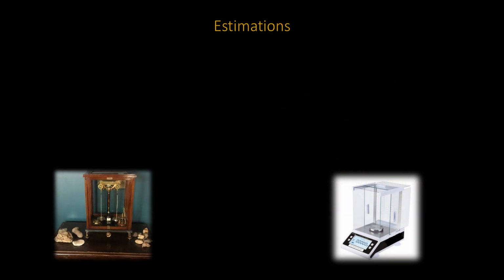It is important to estimate the amount of silver in the bead. This is usually done by conducting a preliminary parting without inquartation. This is done by weighing the doré bead prior to parting and then weighing after the parting. The weight in silver is estimated. It is the difference between the two weights. Now, using this information, the ratio of silver to gold can thus be estimated.